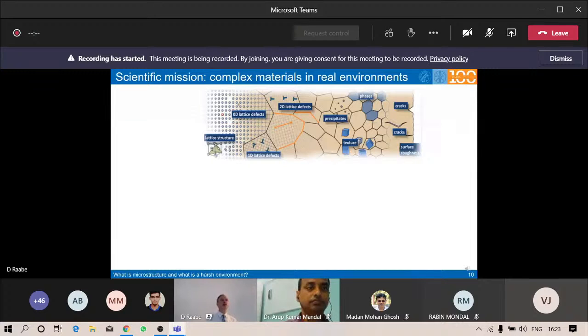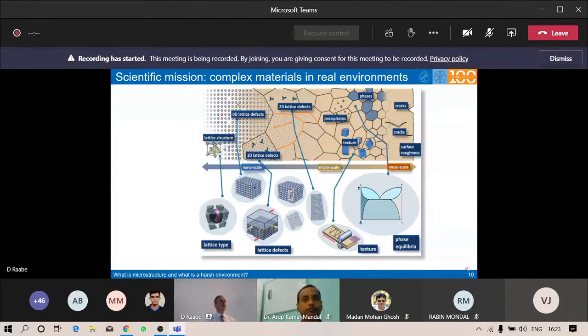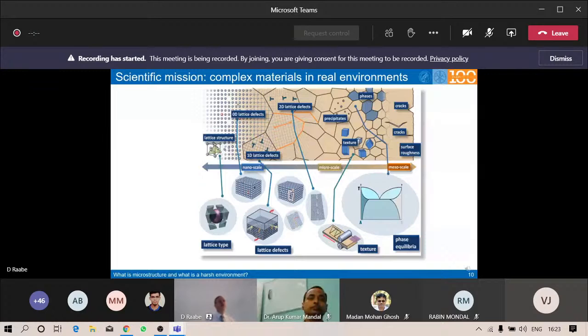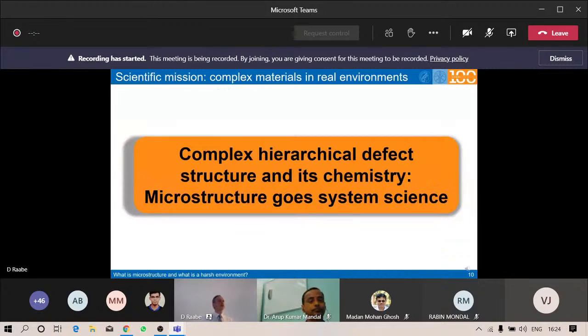So we all know this really complex interplay of microstructures, and as said before, the direction in which they want to evolve is, of course, determined by the thermodynamic potentials, but they are largely affected by the processing, the arising metastability. And we want to understand that material not only out of the microstructure, but also under the influence of the environment, here shown in terms of some diffusing gas atoms like hydrogen or oxygen. That means we have real hierarchical defects, and we have its associated chemistry, and that's where the classical microstructure research goes system science.